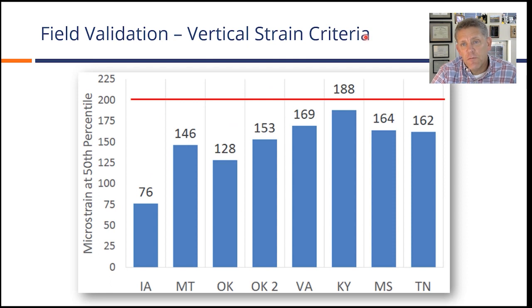What about rutting? Well, if you read in the literature and you look at research that's been done in this area, there seems to be some agreement that we need to look at 200 microstrain vertical compression down inside of the subgrade and control that on average, so at the 50th percentile, for example. And so we took those same test sections that I was just talking about, simulated them, and what we found was that every one of them, the one that came closest was in Kentucky here, every one of them was below the 200 microstrain criteria. And so we felt like that was a good validation, and using that, it seems to give us some pretty reasonable cross sections as well.